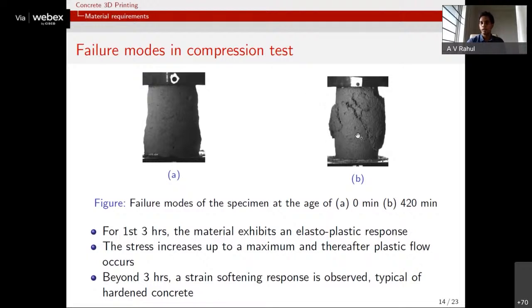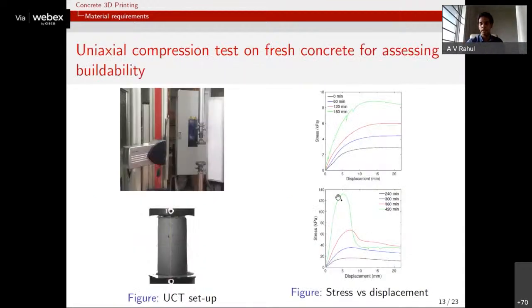But in the hardened concrete, you see that there's enough rigidity formed in the structure. There's some network of hydrates that has started to form, especially if you look at 420 minutes, or 5 to 7 hours in that range. Then you will see that there's a rigid hydrate network formed. The breakage of the hydrates results in the formation of shear cracks, and that, in fact, leads to the strain softening behavior that you see here.